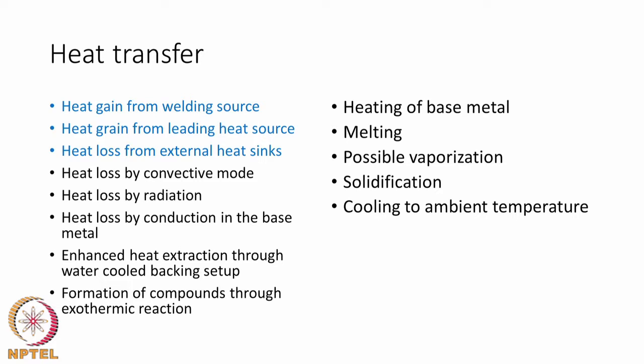And during heating, what normally happens is we have the heating of the base material, and then eventually the melting point will be reached, and then we have the melting of the material forming the liquid melt pool. And then sometimes the temperatures could reach high enough that locally evaporation also can take place. And then eventually when the torch moves ahead, the liquid melt will solidify to form the solid material behind the torch, and then eventually that gets cooled to the ambient temperature. So, this is a cycle where the heat is given so that the material is heated up and then is cooled back to the ambient temperature, and these are dependent on the heat source very crucially, and therefore, understanding the heat source in depth is important.